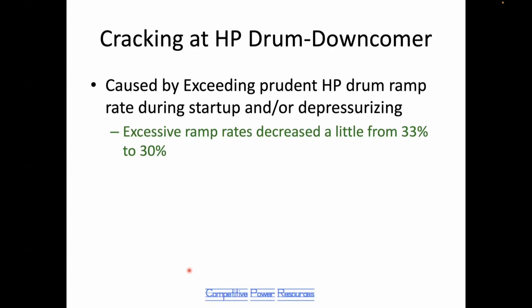This has become, as the units have gotten older, we didn't see cracking in these drums for the first 15 years, once a large number of HRSGs began operating. But in the last 5, 6, 7 years, as units have aged, more and more units are experiencing cracking in the HP drum, generally at the downcomer on the inside of the drum. Downcomer welds, the inside of the drum. So it's very important every time you're in that drum that the inspector look for cracking around that downcomer. If you catch it early, you can monitor it and deal with it and not have a problem. If you don't identify it early and it goes on growing and growing and you don't change the operating procedures to lower the ramp rates, that cracking can become a big expensive problem.